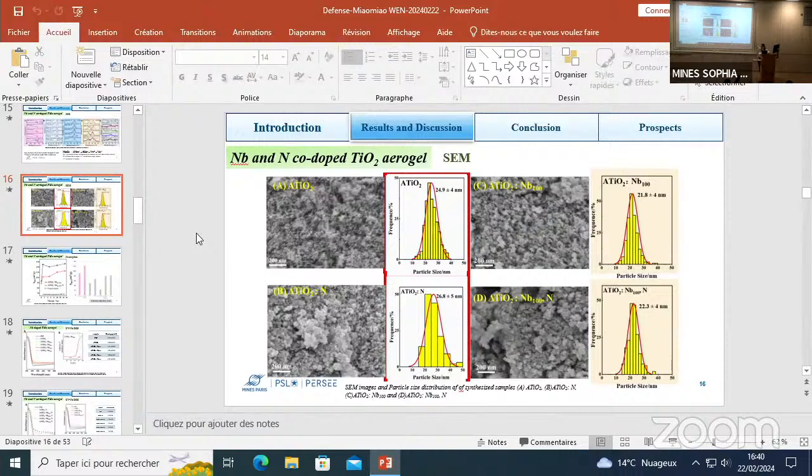Yes, like that. And when we come back, there's going to be space between. That means the porosity is due to the cavity made from an assembly of particles. So it's interstitial porosity, intergranular porosity.